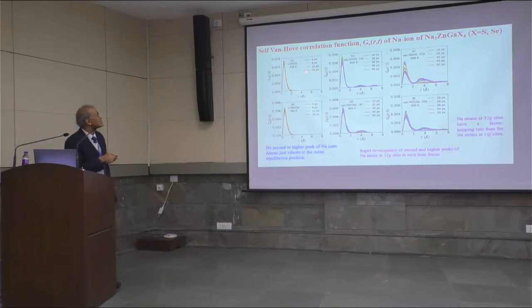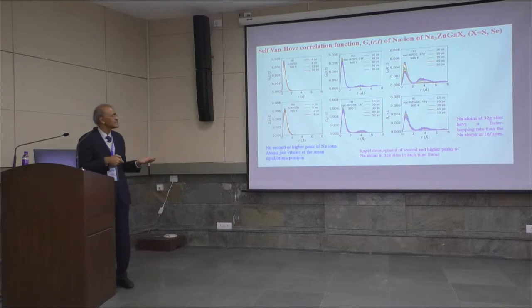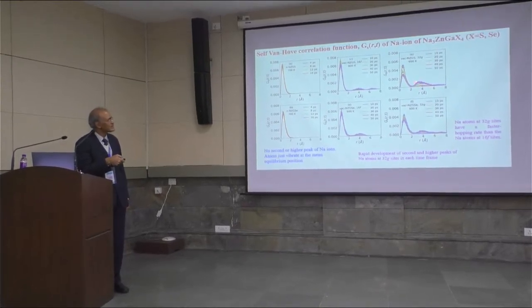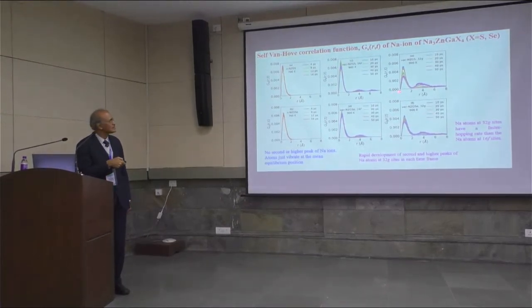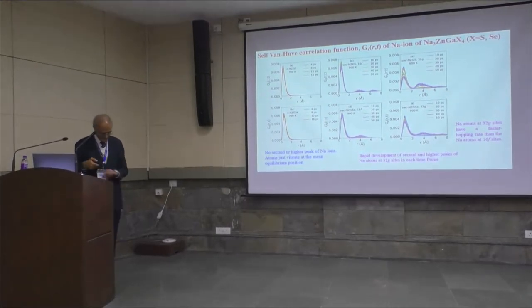Okay, this is again the self correlation function that tells how, as a function of time, the second peak develops. So the first peak is the self correlation of the atom as a function of distance from the initial position at zero time. In the beginning, you have just the phonon kind of vibrations, and as time proceeds, the atom would have jumped to another site at a distance. And so it is the same atom at a later time, located at a different position. So this helps us to identify what the jump lengths and jump times are in this process.